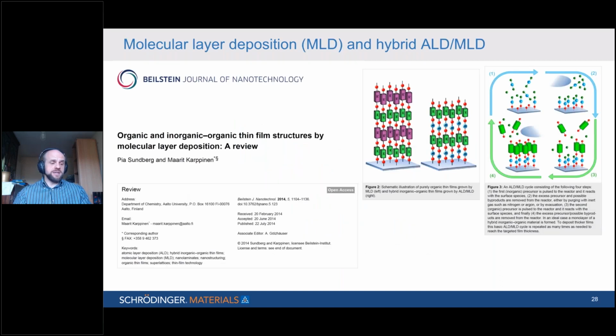So the example that I'd like to talk about is molecular layer deposition. This is a way of depositing organic films or hybrid organic inorganic films. And here I've just stolen some nice cartoons from the review article by Marit Karppinen, which is one of the top groups in producing these type of films. And you can see the schematic there of how the films are produced. The organic groups are linked by reactive moieties, and each one is laid down sequentially one after the next. So you get a green layer, then a purple layer, a green layer, a purple layer, as you turn on and off the precursor pulses. Alternatively, you can include an inorganic metal, and that's shown in the next cartoon to the right there with a blue metal ion.